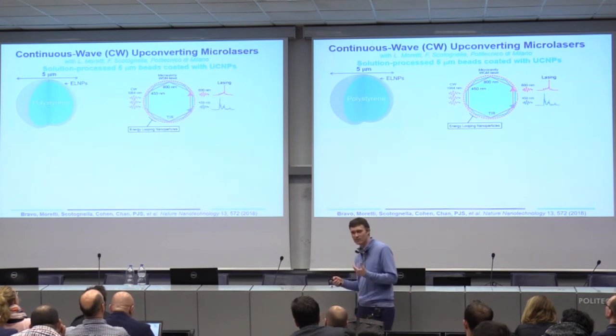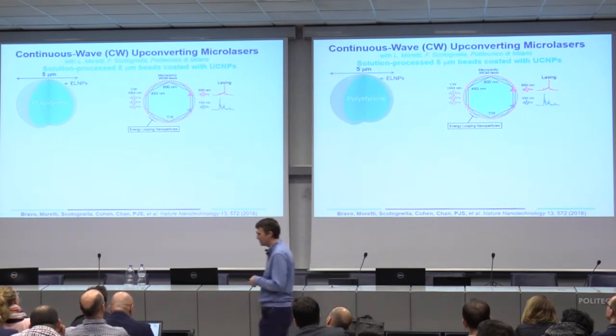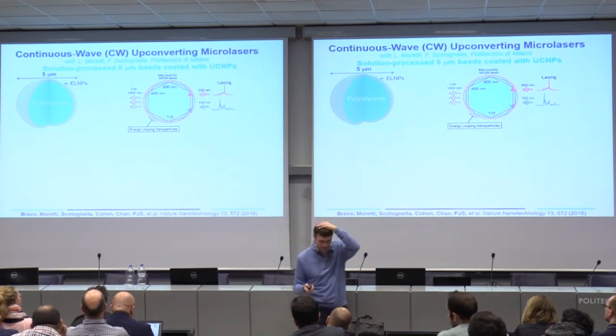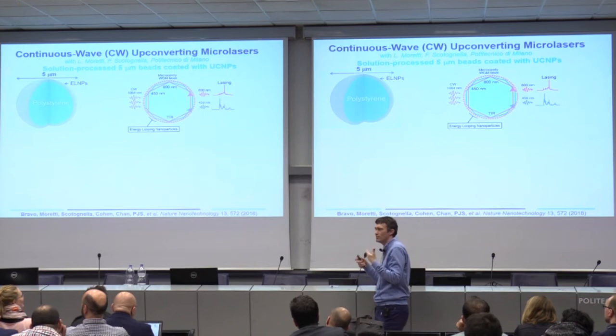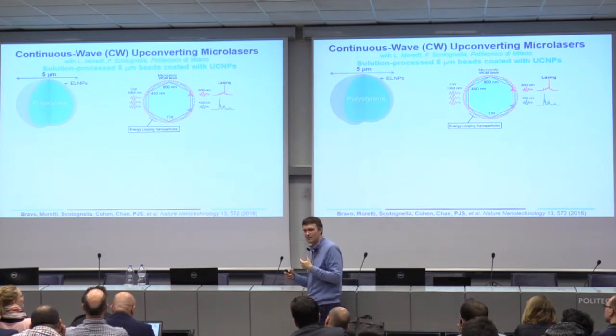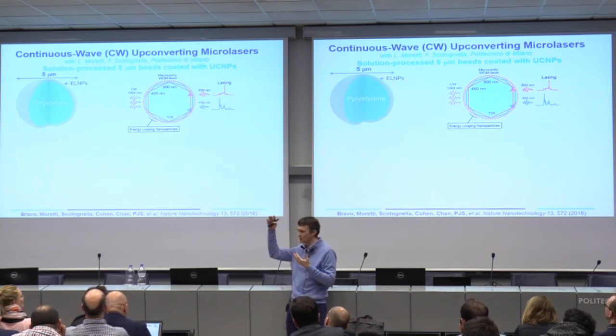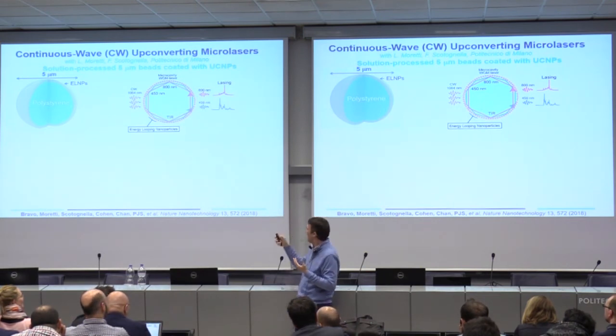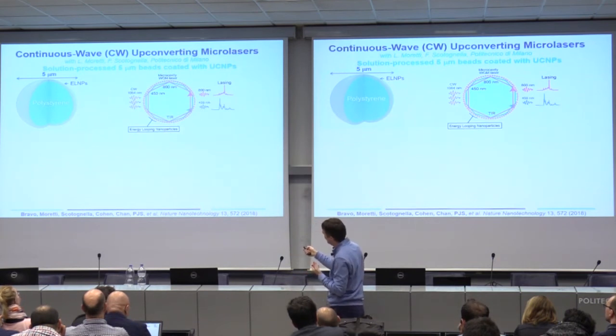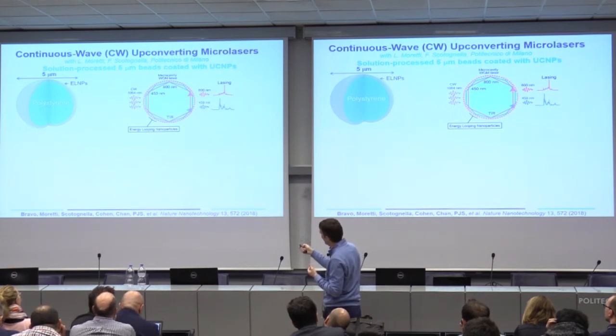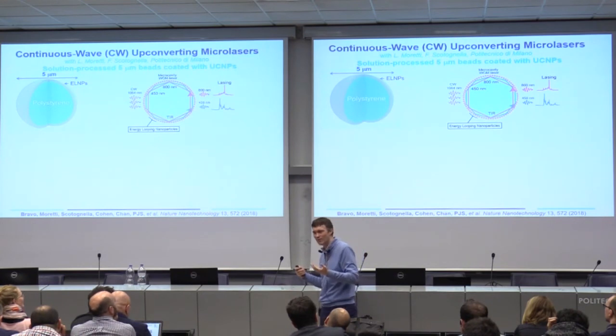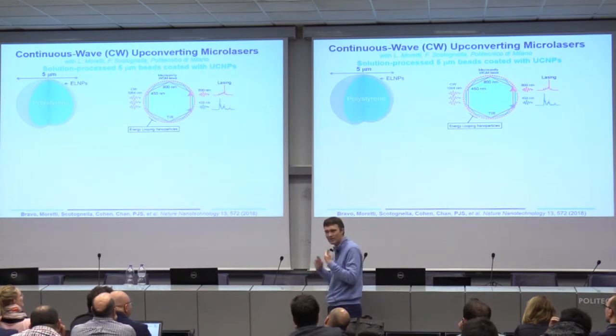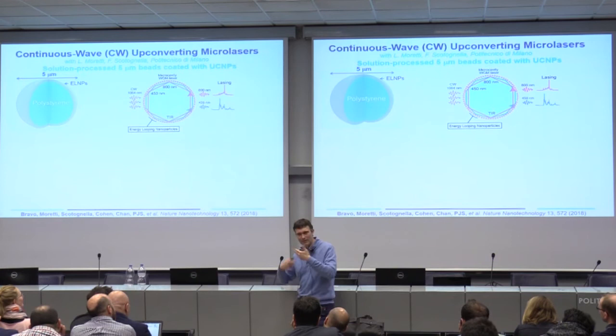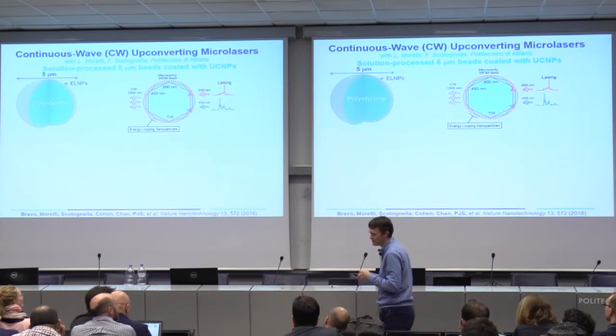And so we did something very basic. We took our very good materials, with Francesco and Luca Moretti here, and we put them around something very, very simple, these polystyrene beads. Essentially, they're whispering gallery mode cavities. You just get total internal reflection, again, as we heard in the last talk, that forms these nice little optical modes inside the bead. First you shine 1064 light inside the material. That goes around and around, optically pumps your upconverter, and then some of the emission goes back into a similar mode, and now you have this gain material in that mode, and they start to lase. That was the idea anyway.